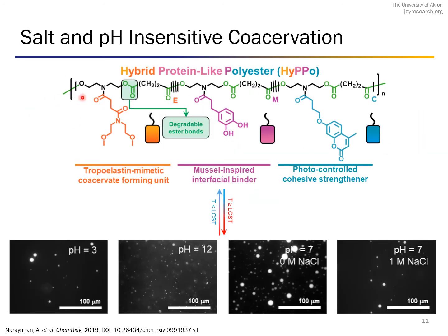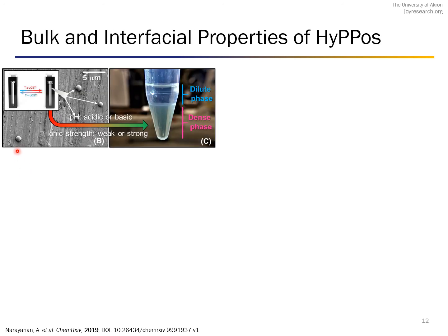So in my study, we have created this hybrid protein-like polyester, which has two different protein-inspired units. First one being the tropoelastin-mimetic unit, and the second one being the mussel-inspired interfacial binder, which provides cohesive strength. These polyesters undergo a lower critical solution temperature based transition at higher temperature, and are stable in all ranges of pH and ionic strength. The droplets formed from the polyesters above the LCST condense to form these dense and dilute phases.